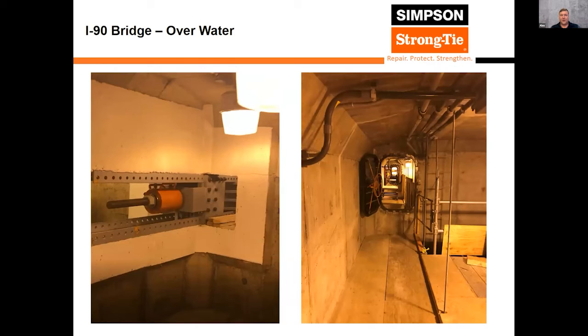Looking at the left here, you have a PT anchor point into the existing concrete pontoon. On the right-hand side, you're going to see man doors running the length of the pontoons, to give you an idea of how long it is and how many bulkheads we needed to get through with FRP. Like I said, this jack on the left is going to pull those strands into tension, and that tension is going to compress the entire structure between anchor points to keep it in compression. That way, as it moves, the concrete stays in compression and the steel takes all the stretch. That's a very good system for allowing a concrete structure to move and not fall apart.